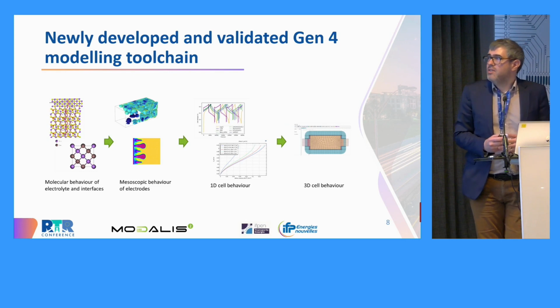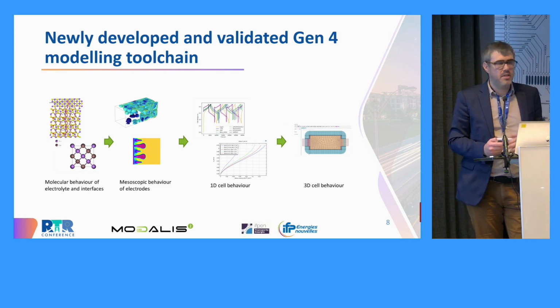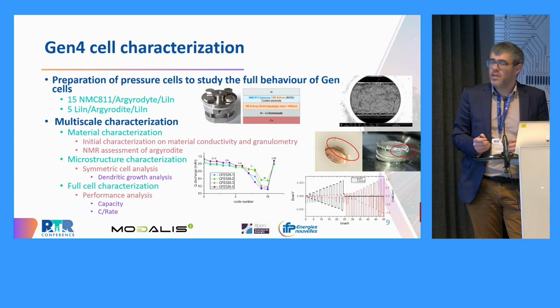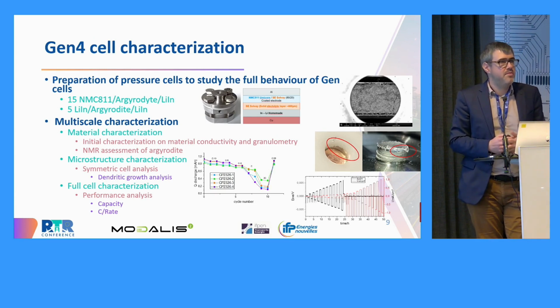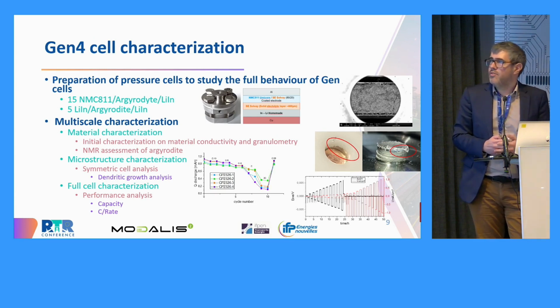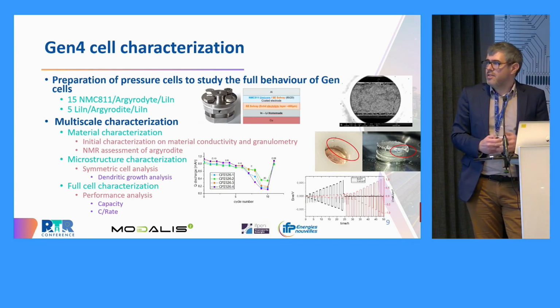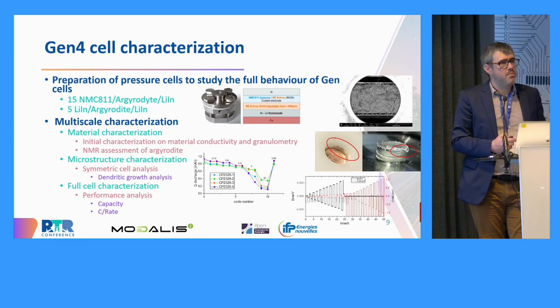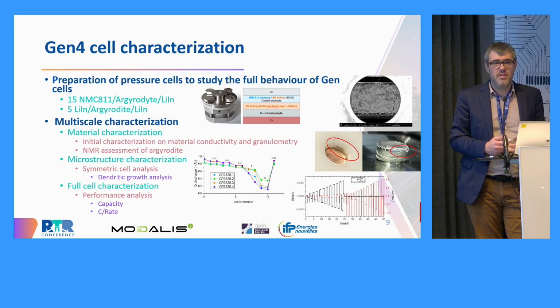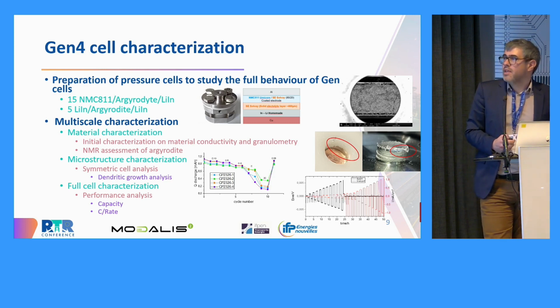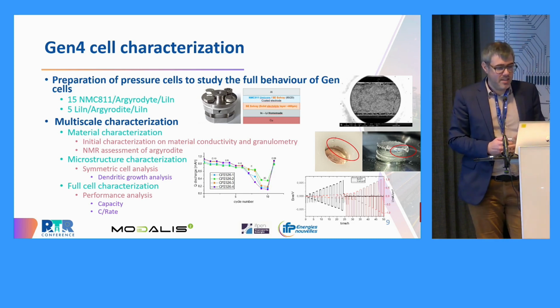The same kind of approach was also done for Gen 4 batteries with solid-state electrolyte. So we had to prepare specific cells for this kind of material, and it was already a challenge for Gen 3B, but for Gen 4, we had an even lower TRL, so we had a lot of surprises linked to the behavior of the cells compared to what we expected 5 years ago. We were able to build 20 cells in pressure cells with lithium indium as the negative electrode, NMC 811 and argyrodite electrolyte, and we did the characterization.